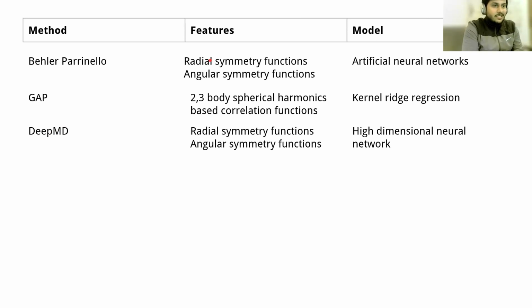Their architecture is essentially the same as Behler-Parrinello, just that they call the step from going from your structures to these symmetry functions embeddings. That's, let's say, the lingo that is used more in terms of machine learning. It's a more general term. And their construction of these radial and angular symmetry functions is, let's say, more universal than in the Behler-Parrinello scheme, but it's exactly the same. And instead of an artificial neural network, you just use more layers in this case, and that does the trick.